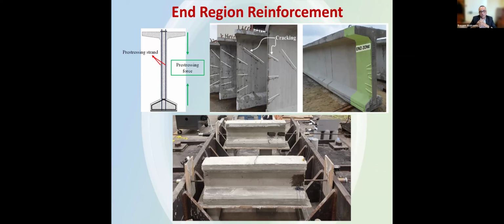When it comes to AASHTO or to PCI guidelines, they provide recommendations for using a lot of transverse reinforcement at the end region, which makes a lot of precasters unhappy, unfortunately. So we tried a new concept. We said, how about if we apply simply, transverse pre-stressing by throwing in a couple of end stirrups made of SMAs. So we tried this concept on small scale specimens like this. Looks like an AASHTO type girder. And we only used one stirrup, number 2 stirrup made of SMA, 2 legs.